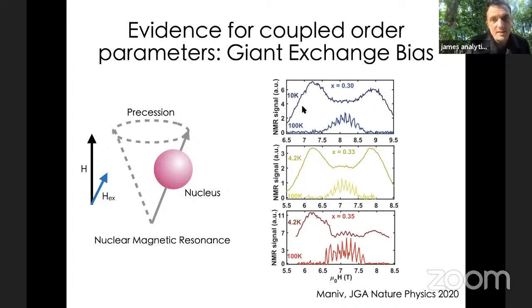The second thing that we see is that as you decrease to lower temperature and you go to the antiferromagnetic state, we see two broad peaks associated with essentially the spin up and spin down configuration of the antiferromagnet. Now, this would probably be agnostic to whether it's stripe order or whether it's zigzag order, assuming that the ordered moment remains the same and the local exchange energy remains the same, I suppose. But again, we see the same kind of splitting in each one of these intercalations.